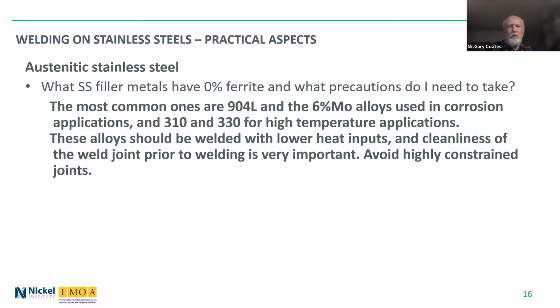They have 0% ferrite in the filler metals, and you have to be very, very careful when welding those alloys, with lower heat inputs than you would use for standard grades. Cleanliness of the weld joint is very important, as is avoiding a highly constrained joint, where, as the weld cools and shrinks, it puts stress into the base material. If it really can't move, then it can easily lead to hot cracking.